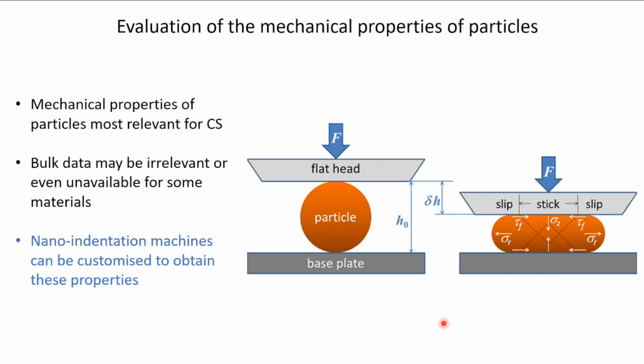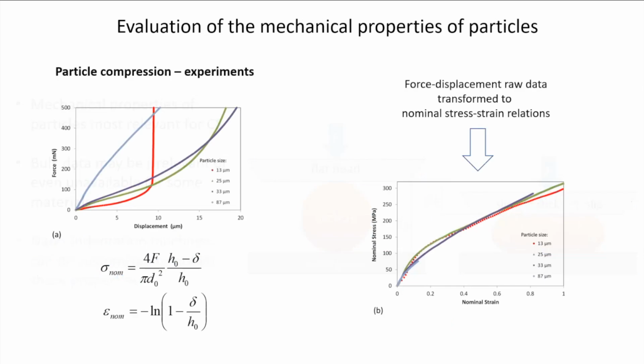Now, why did we do that? Because there is an intrinsic difference between the microstructure of particles and bulk material, because they are produced in a different way. So the microstructure is forming at a very high cooling rate normally if you use atomization. So that's one thing. The other thing is that sometimes we don't even have the bulk data. So for some materials, for instance, they are normally produced not in bulk form, but in powder form. So because of that, we need to come up with a way of measuring these mechanical properties.